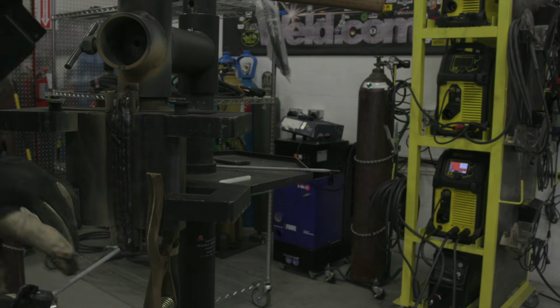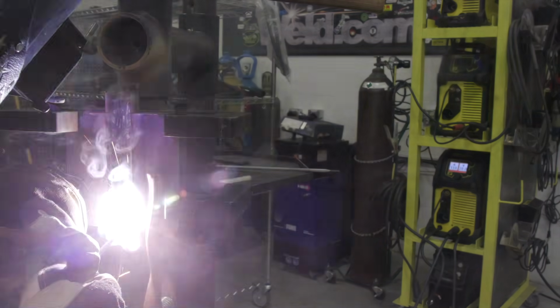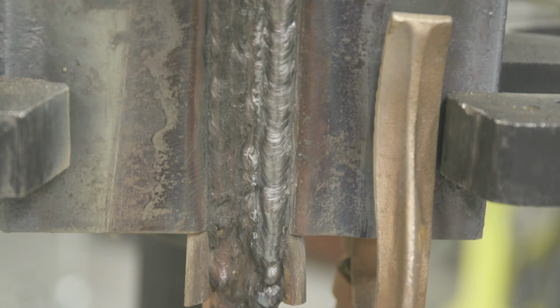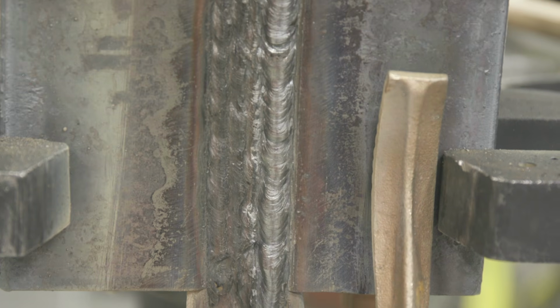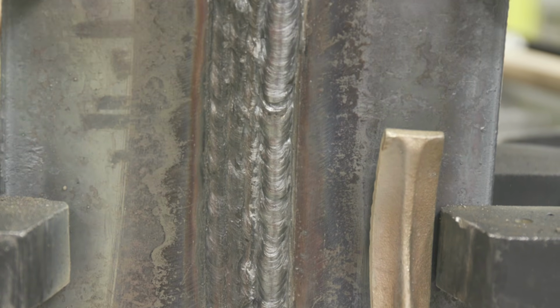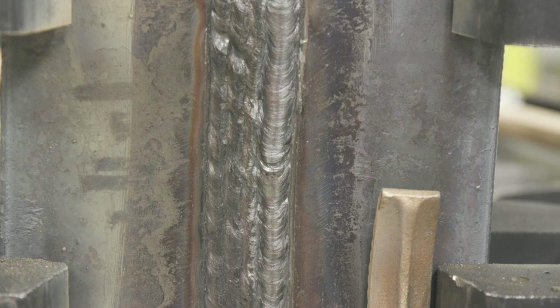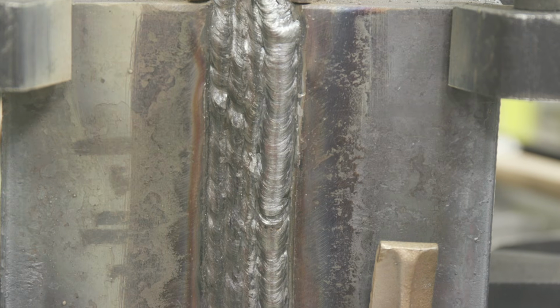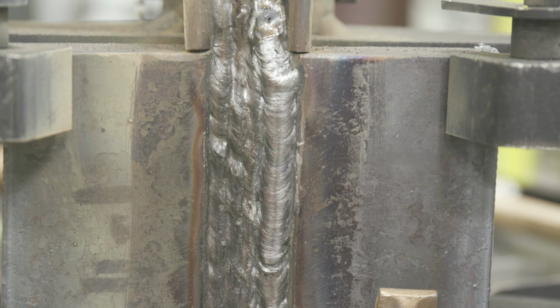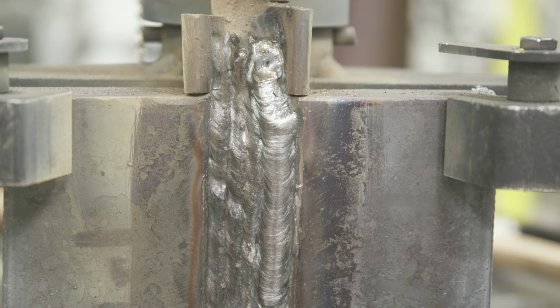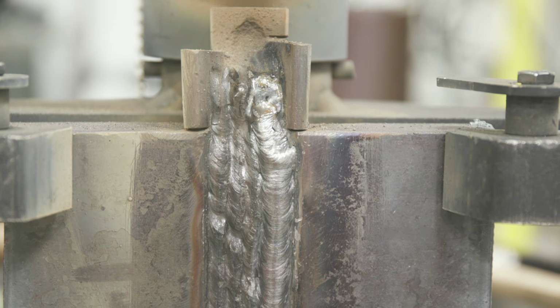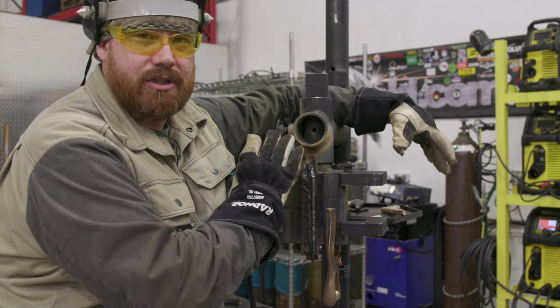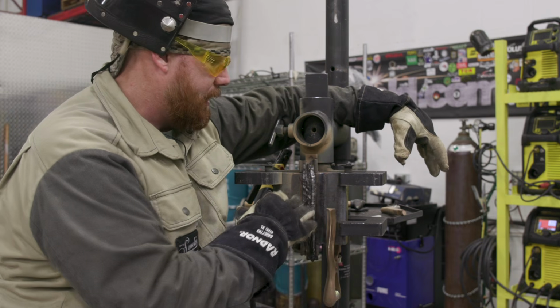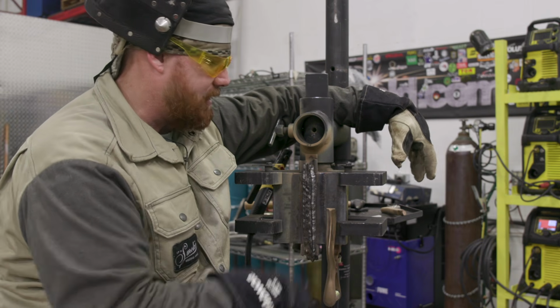Also, I had a couple low spots in here, so I just ran a couple short stringers to bring this back up to where the rest of the profile is. You'll notice when you start running these, it'll be a little bit lower down here and a little bit higher up here, probably because we change technique or travel speed as we're going through. So I ran a couple short ones over here, brought everything back up to profile, and then continued my sequence right over that. When we cut all this apart, this whole internal section is going to be solid weld metal if we did it right. We shouldn't have any porosity, shouldn't have any slag inclusions.